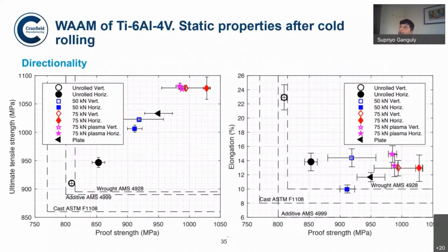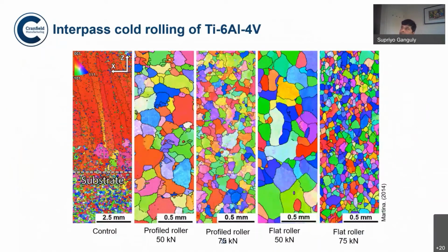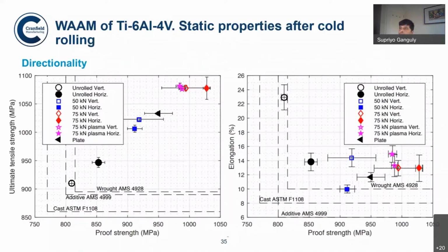Now I will talk about the directionality, or the anisotropy, that you will see when the grain structure is completely aligned to the deposit direction. If I go back to the previous slide, the left hand side micrograph shows the strength that you are getting, shown here in the filled black and the empty black circles, where you can see there is a very significant difference between the two directions. The vertical is always lower as compared to the horizontal. Now, when we roll it with 50 kilonewton, the differential strength between the two directions is now quite less.